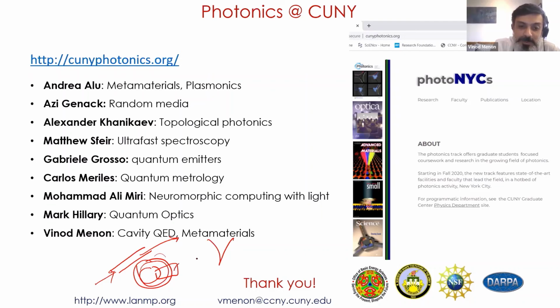And what they did was to modulate the dielectric property of this 2D material. So this was a monolayer semiconductor, or I don't remember if it was monolayer or bilayer, but they modulated the dielectric property of this material. But what was interesting about this result was they did not modulate this. They were operating this device in the infrared. I don't remember if it was 1300 or 1550, but they were operating in one of these near infrared windows. But you know the exciton resonance of these materials is in the visible.